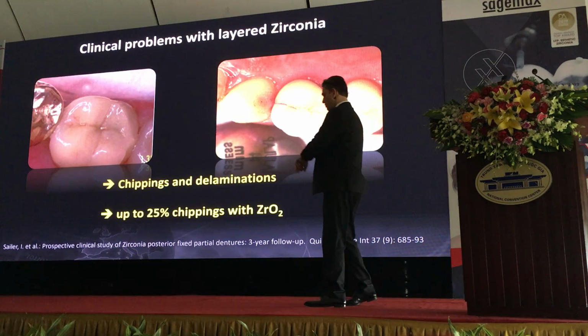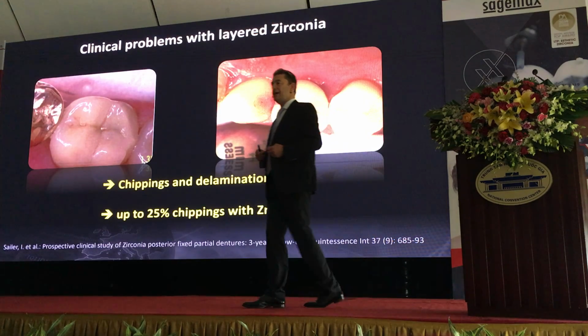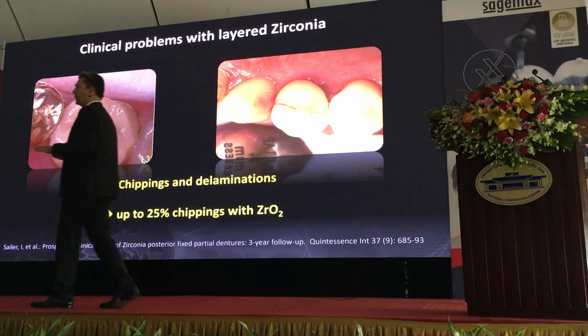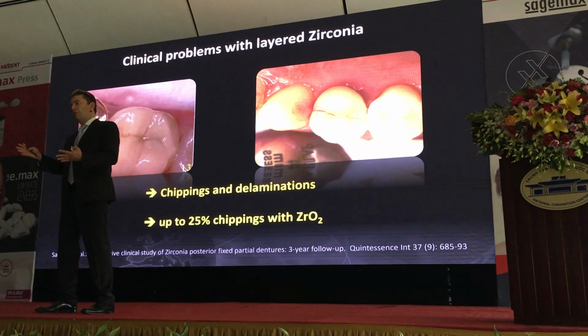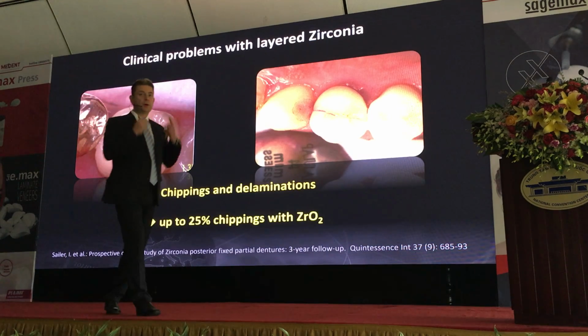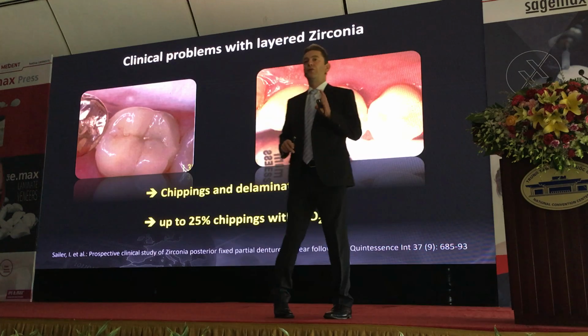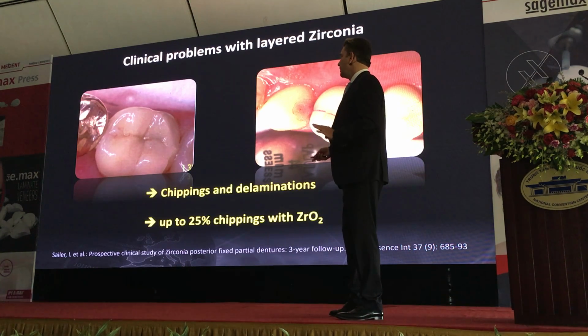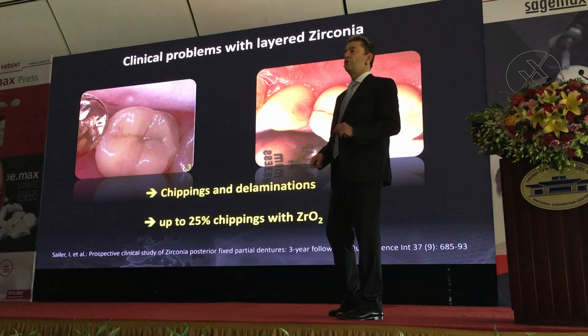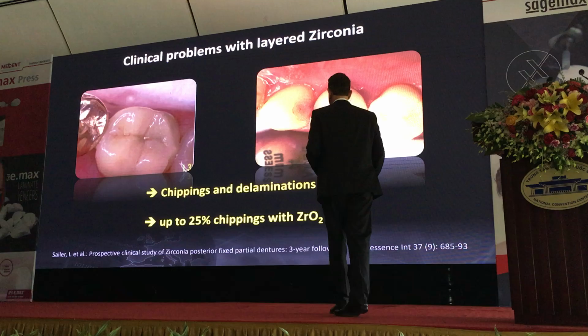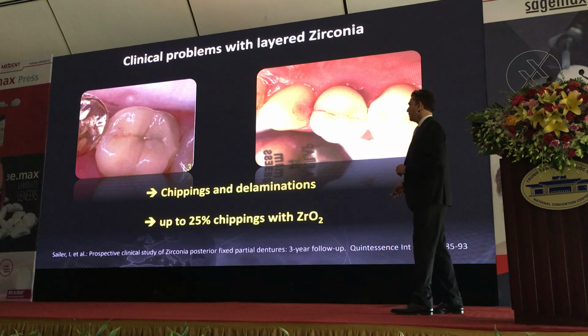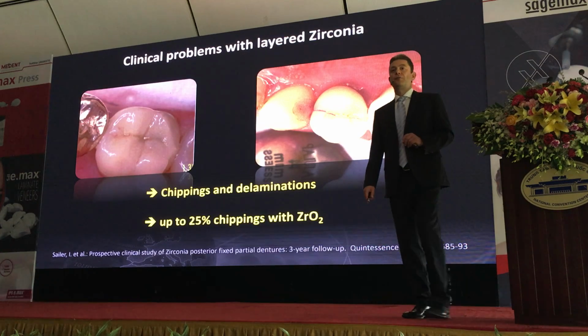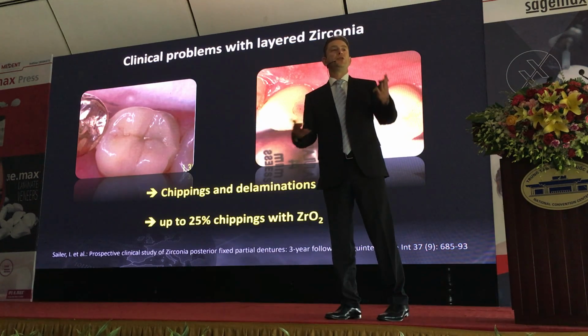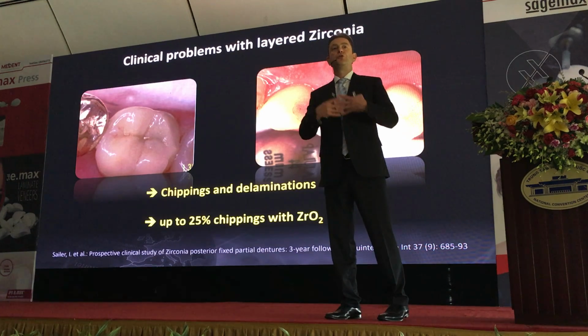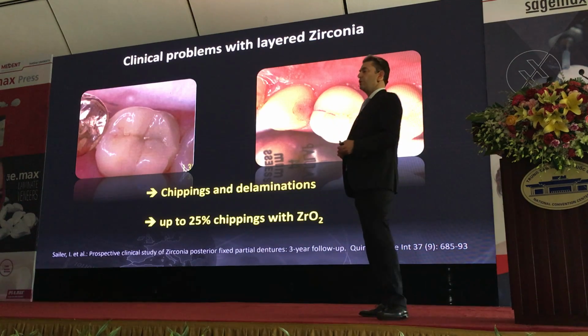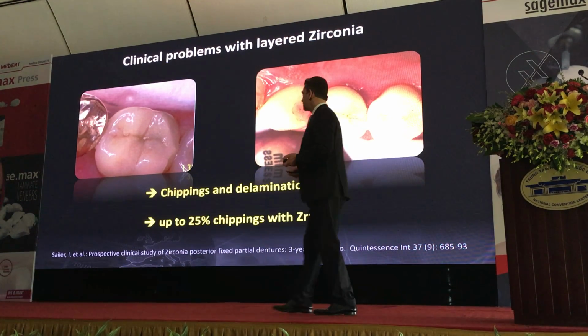Okay. Good. So, I told you that today we don't want to use restorations that have a layering, like a veneering ceramic. In the posterior, at least, we want to focus on monolithic restorations, because we have seen a lot of chippings with zirconia restorations that have been layered. You can see here in this study, we had up to 25% of chipping after 3 years. Of course, it's very annoying because you need to repair it. The patient comes back, you need to do some repair of the zirconia restoration, and so it's not very nice.